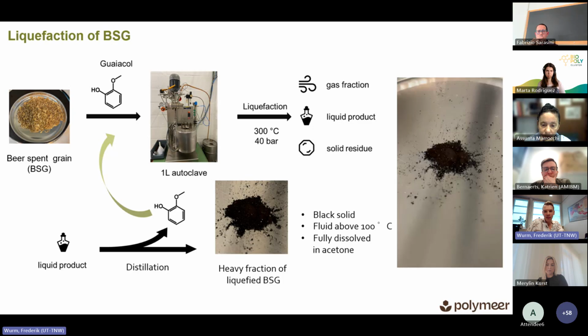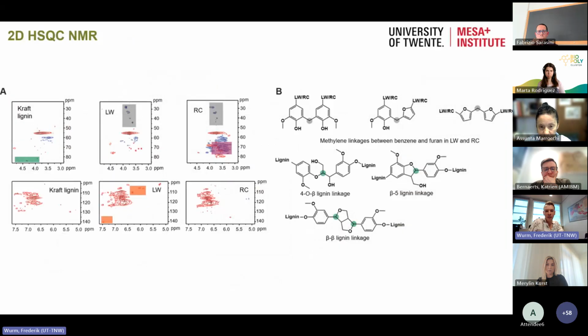And this black material is interesting from the chemical structure. It's broken down the lignin structure. When we look in detail in the 2D NMR, I won't go into the details here, but we can compare different fractions of these liquefied materials. They have similar structure to kraft lignin, but they also have other compounds that you don't see, for example, in kraft lignin. And also there the question will be, how can this be biodegraded or bioassimilated in the soil?